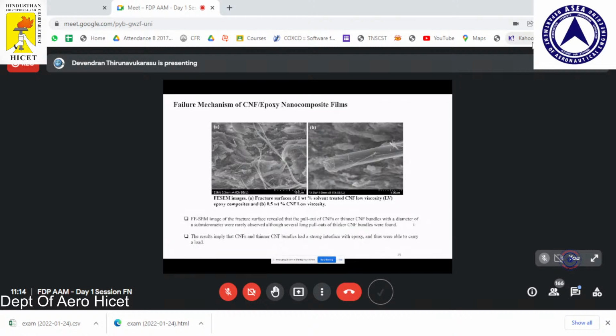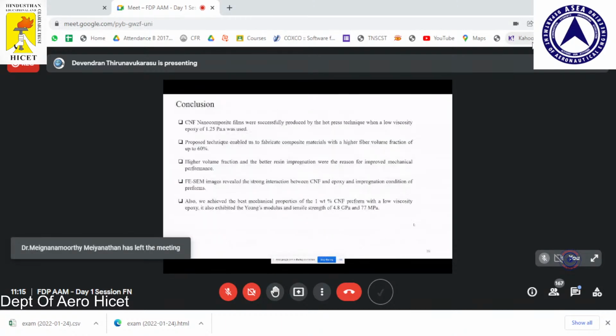The nanofibers also show a pullout mechanism. So currently we are thinking that we have to find the breakage and failure mechanism of nanofibers. That is a new trend going on: if we are using nanofibers or nanomaterials, we have to study the failure mechanism of that material. So here we tried to observe what kind of failure mechanism happened, and we found some fiber pullout and also some resin breakage. But mainly we observed fiber pullout in our research.